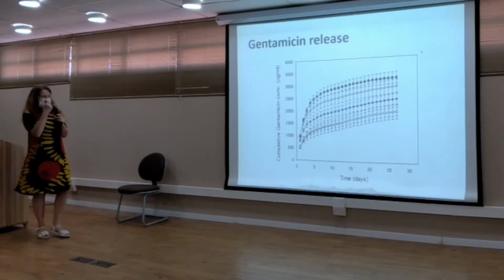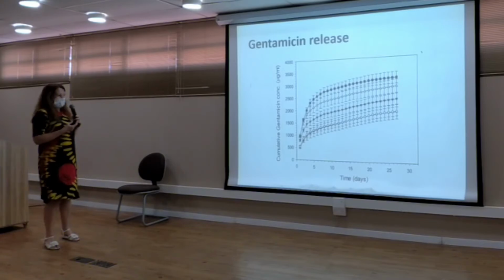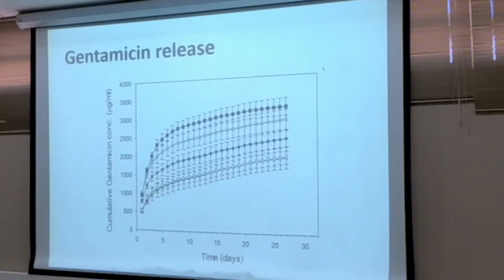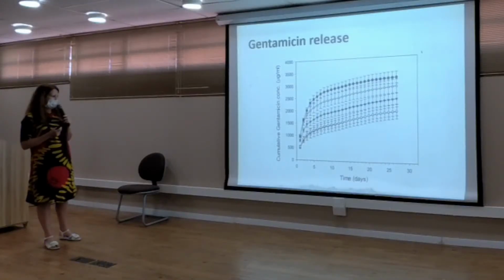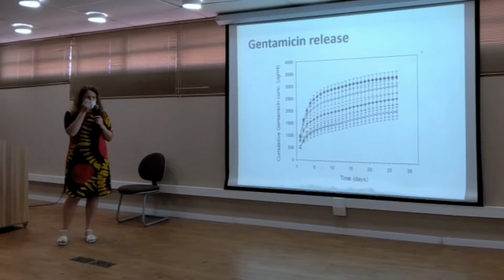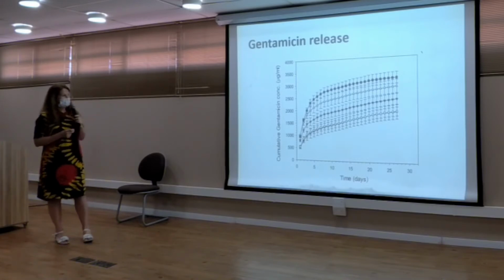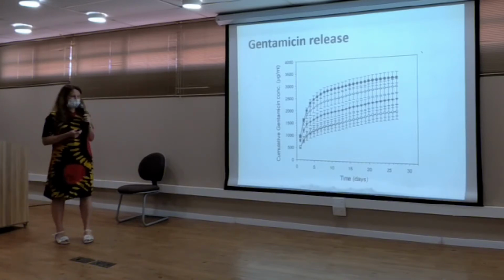And this is the result which we really wanted to have eventually. So we did release from these nanoparticles over a period of 1 month plus. And as you can see, in all formulations which we prepared with a different combination of layers, we have controlled, prolonged release over a period of 1 month. So we did achieve our target, what we wanted. Our clinical collaborators were very, very happy with the results.